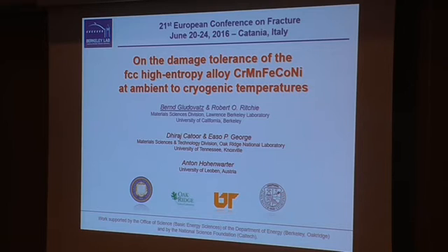We get very large strengths and fracture toughness numbers through planar dislocation slip and nanoscale deformation twinning at the lower temperatures, which gives us a very high strain hardening exponent, prevents necking, and that way we get quite up here to the top of typical metals and alloys, where these materials compare quite favorably to the best austenitic stainless steel that we have today,